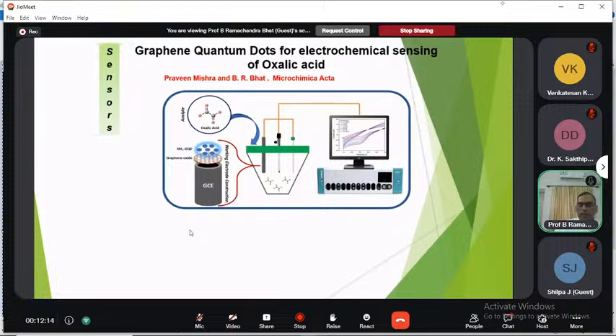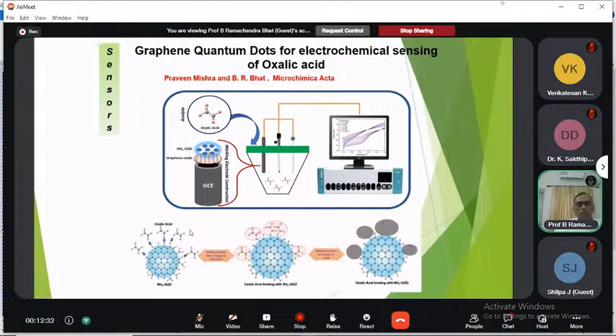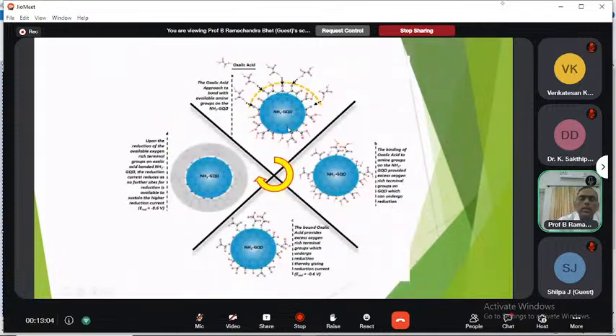Oxalic acid is present in the body, and it forms calcium oxalate, which is nothing but the kidney stone. So one has to monitor the concentration of oxalic acid in the body. You can see that this is the amino functionalized graphene quantum dot, and the oxalic acid approaches it and forms a bond here with this oxygen, and more oxygen is available here because of the oxalic acid. Here the reduction of a free acid group takes place. This is the graphene quantum dot.